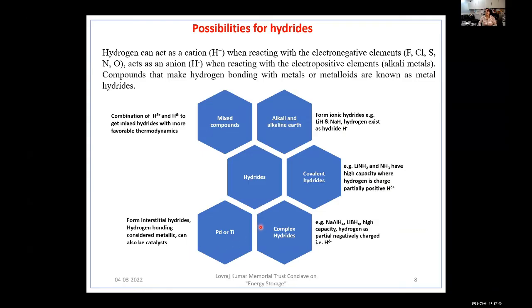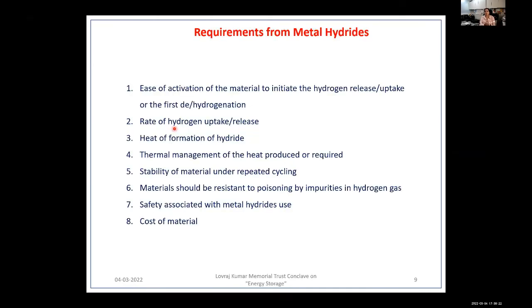Now, each of these has its own challenges. Some form very strong bonds, as in the case of complex hydrides, so that if you take out hydrogen, the dehydrogenated product is very difficult to regenerate. The spent fuel and getting back the initial compound is a problematic, energy consuming process. So what can be done is we can have a combination wherein both these components are put together to make a mixed hydride, and that could give us better thermodynamics using those classes of materials.